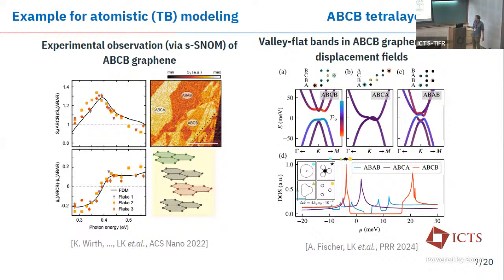They also find other types of stacking, the 3 different inequivalent stacking types in tetralayer graphene. And for all 3, it was a straightforward task using the DFT-inspired tight binding model to describe those optical conductivities and unambiguously state which of them should be ABCB. We also continued to do some analysis of the possible superconducting and spin density wave orders in ABCB graphene.